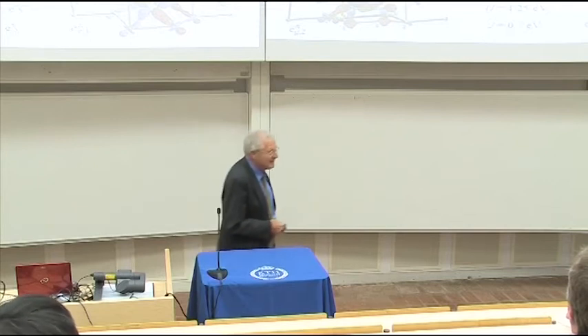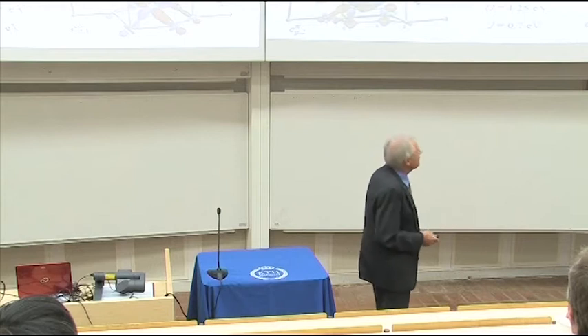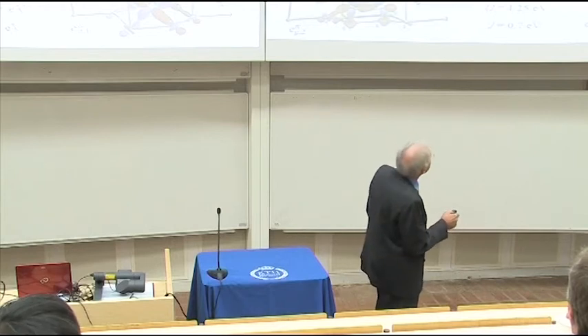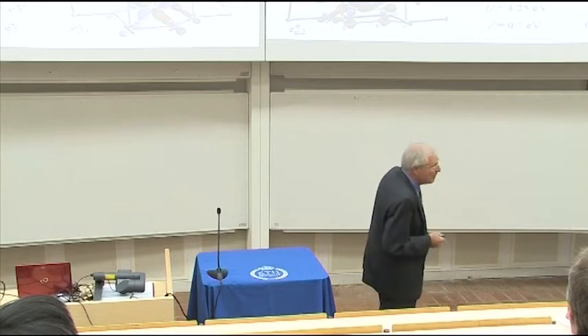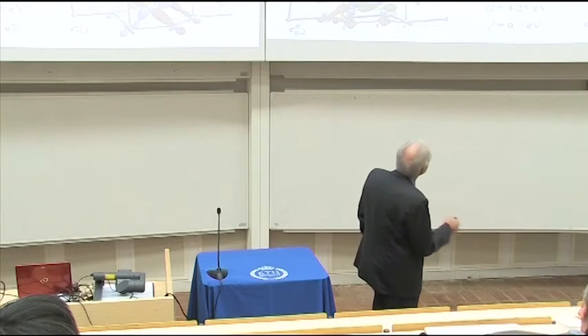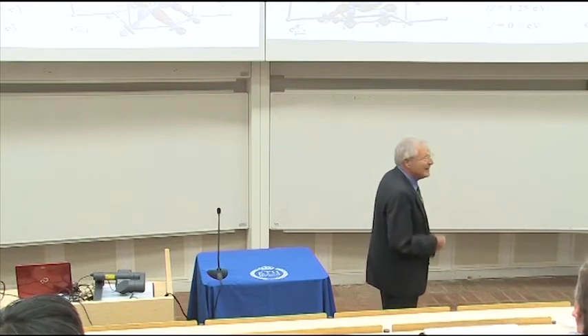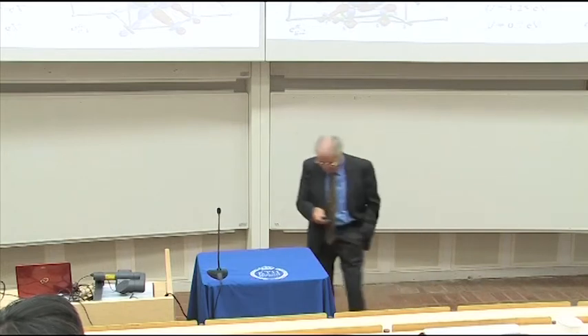But this is not the way it was looked at for many, many years. It was believed to be a real Mott transition in which you have one band that breaks. It was believed that you have bonding between this guy and the other one sitting up here - they make a chemical bond. Then you have 1 electron left, and that electron was sitting in bands, 1 from each side, and it is that correlated band with EG pi orbitals which makes a Mott transition.